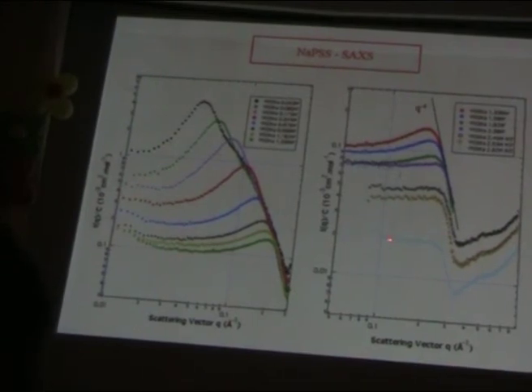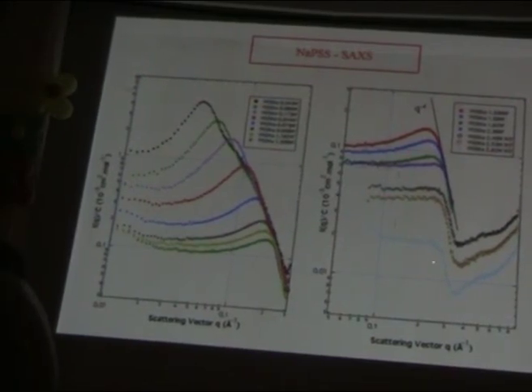So you increase the concentration, so the peak moves here. It is the electrostatic peak. So when you increase the concentration, because you increase the ionic strength, of course the peak disappears. But at a certain concentration, you have another peak. It's always a correlation hole. This peak here is much more a steric correlation hole, not an electrostatic correlation hole, if you want. And in this case, you can see that there is another behavior. It's not so easy, but you can see another behavior.